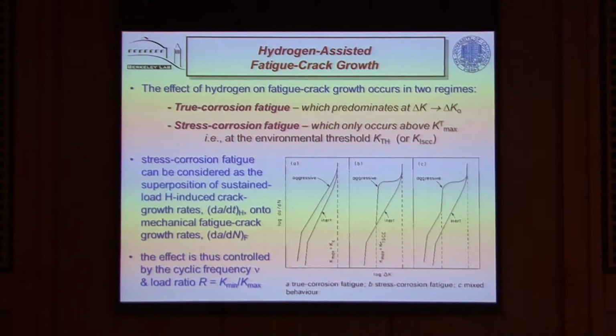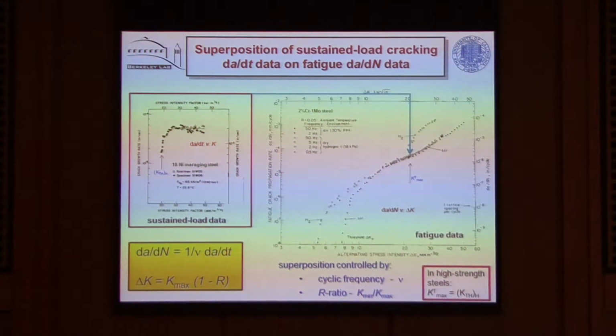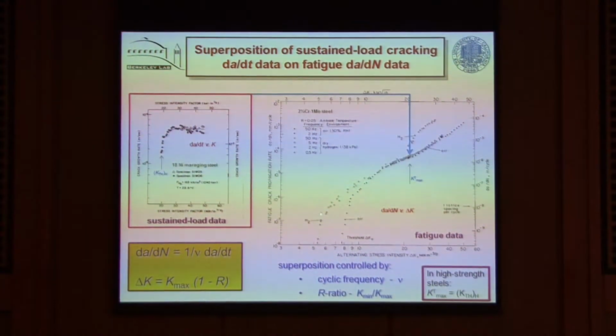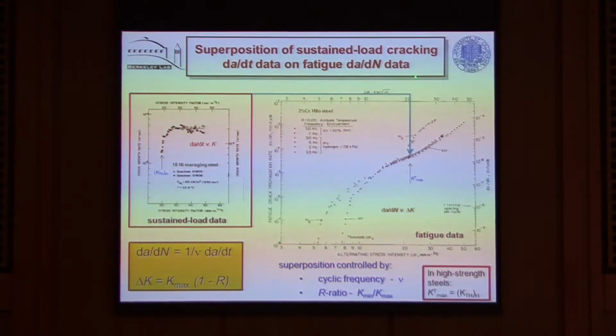Now, how can we take care of this effect here? This is a rather interesting phenomenon which has been known for some time, that we can generate superposition. This is the rate of growth of a fatigue crack, dA/dN, the crack growth rate versus the stress intensity. There we have the effect in air, and then we put it in hydrogen, and we get this sudden acceleration. And this can be basically achieved by superposing this data onto the fatigue data. But there are things we have to think about here. This is K, and this is delta K. So where this superposition takes place on this axis depends on the relationship between the cyclic and monotonic loads, the so-called R ratio, as it is sometimes called. And in this axis, we have dA/dt, and this is dA/dN. So the superposition in this direction depends on the frequency of loading. And so depending on the relative frequencies and the load ratios here, this superposition can take place at different points in the horizontal and vertical axis, but in a very predictable fashion.